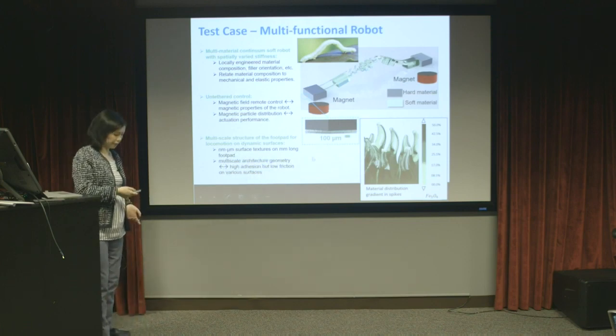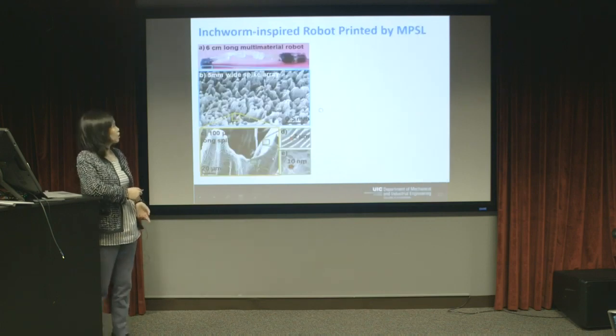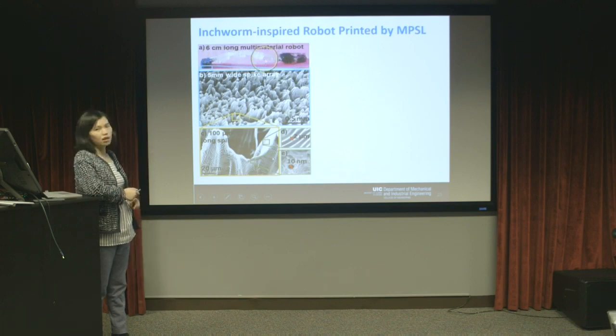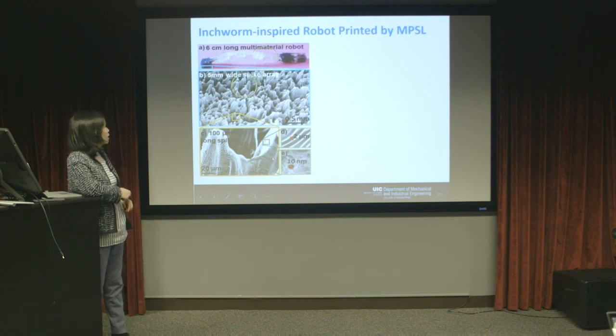This setae-like structure is multiscale, so it should contain features from nanometers to micrometers. The reason we designed it this way is because we want to have high adhesion but low friction on different surfaces. This is the fabricated robot, and as you can see, it is around 6 centimeters long, and about 5 millimeters wide. If you look at the bottom surface of the foot under a microscope, you can see that it has a spike array. If you look at a single spike, you can see very uniform creases on the spike surface. The crease width is around 2 micrometers.